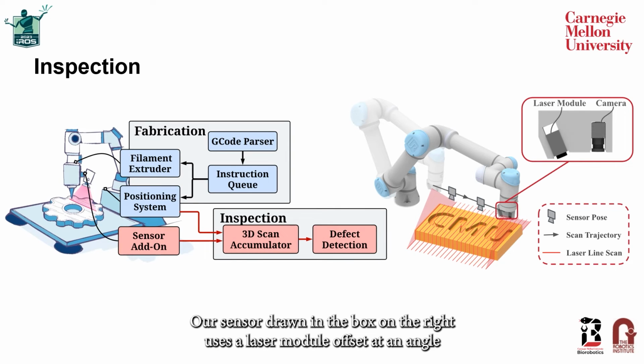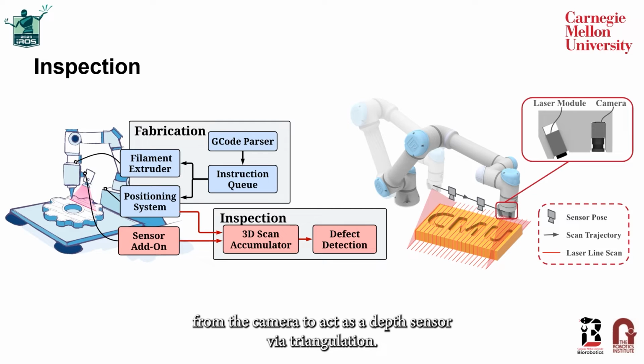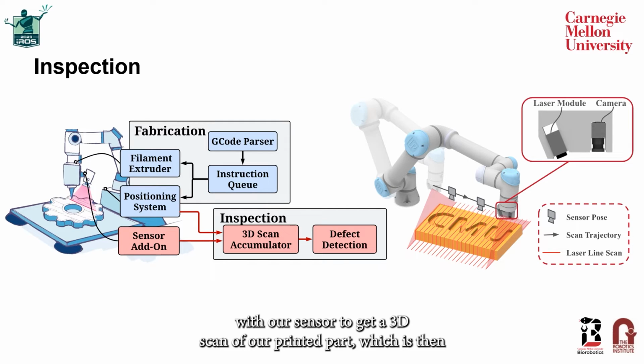Our sensor, drawn in the box on the right, uses a laser module offset at an angle from the camera to act as a depth sensor via triangulation. After each layer completes, we perform a linear coverage with our sensor to get a 3D scan of our printed part, which is then passed to the defect detection pipeline.